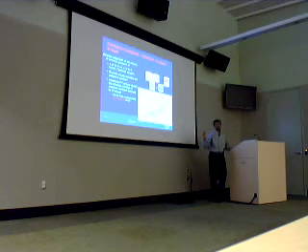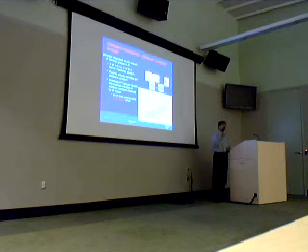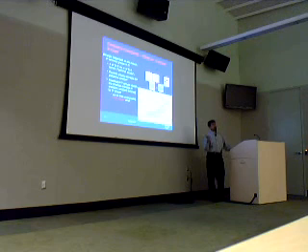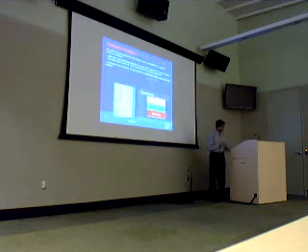And this was essentially done in 2001. Since 2001, Intel has been putting these kinds of materials into the chip because they reduce the RC delay. When the electrical switching comes in, you want very low capacitance in this material. That's why we reduce the dielectric constant. In the front end, we have to increase the dielectric constant. That's a different effect.